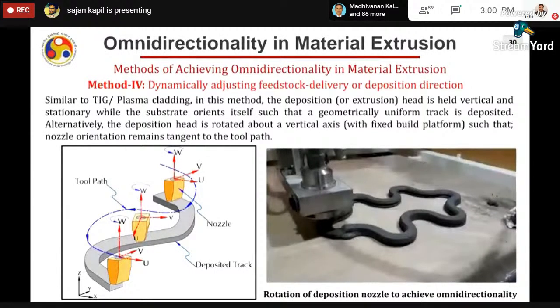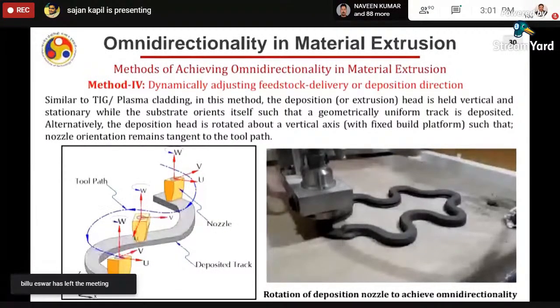What we need to implement is a method. Mostly in this type of systems, method 4, which is dynamically adjusting the feedstock delivery or deposition direction, is implemented. Similar to TIG and plasma, in this method, the deposition head is held vertically and stationary while the substrate orients itself, such as the geometry based on the path, or sometimes the head also rotates. As you can see in this diagram, when I'm moving on a nonlinear trajectory, what is happening? The head is also rotating. It is not coming in a straight line. If the head was coming in a straight line, you would achieve different widths in between. Hence, to make the process omnidirectional, you need to rotate it.